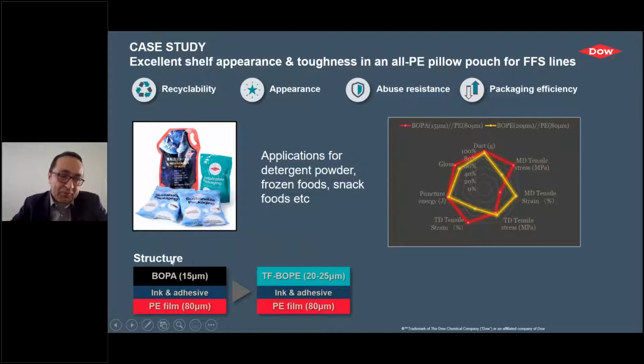And the approach is to replace a multi-material multi-layer structure with a monomaterial multi-layer structure, replacing polyamide with polyethylene. You see, the performance is quite similar. There are slight performance differences in tensile strength and elongation, but still this gives a very good opportunity, a very good alternative to non-recyclable multi-material multi-layer structures.